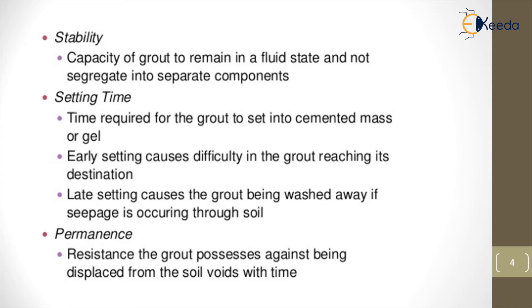Setting time is the time required for the grout to set into cement mass or gel. Early setting causes difficulty in the grout reaching all the voids, whereas late setting causes the grout to be washed away if seepage is occurring through the soil.